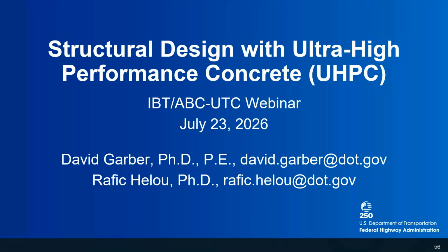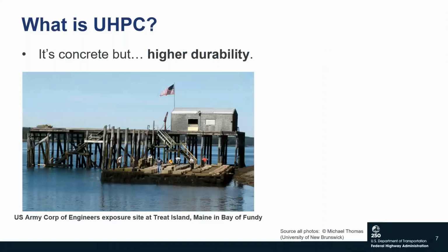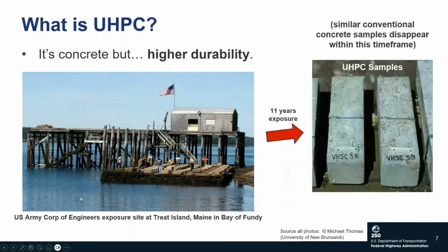You had a picture of that in the main presentation, and it looked like it held together. You could just see a few rusty spots on the top of it, but it was pretty good. Yeah, so with corrosion, if there is a fiber at the surface, it will corrode and go away, and that is what you see here on the screen. There's a brown stain from the fibers. The fiber's not there anymore, but that is the extent of the discoloration or the protrusion into the specimen. So it's just the surface, mainly a cosmetic thing. Nothing that the water won't go inside.